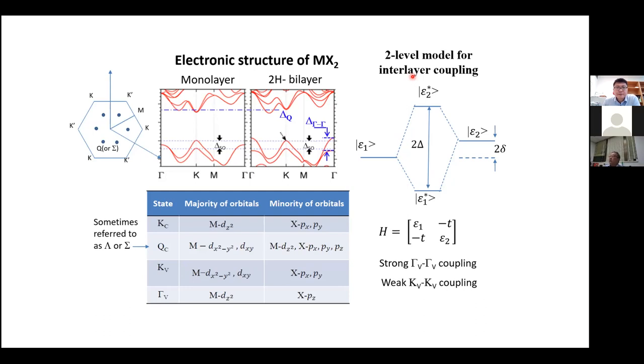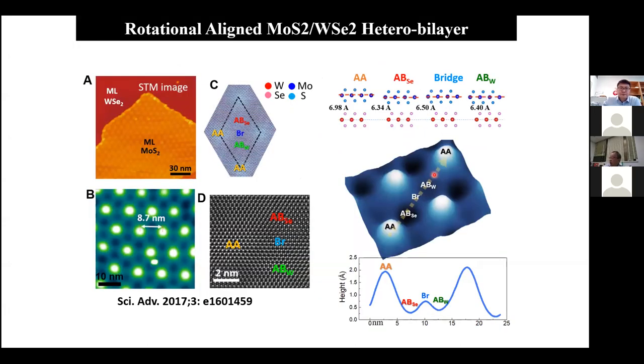But on the other hand, you can understand the interlayer coupling if you take the monolayer as a constituent and you apply K conservation, right? How the things align. If you choose any one point, say a state in one layer and a state in the other, then you can use a hydrogen molecule model or any kind of molecule model, and they couple and form the bonding state and the antibonding state. And that is really this two-level model for the interlayer coupling. And almost everything can be understood that way.